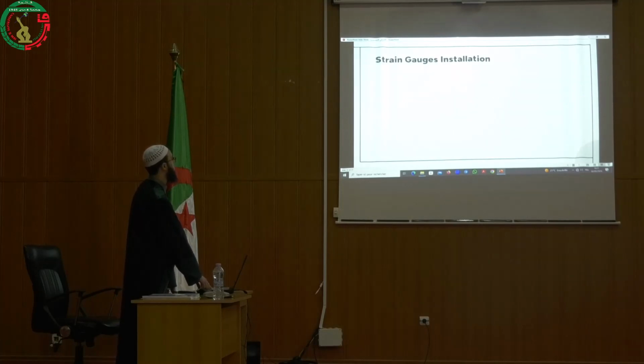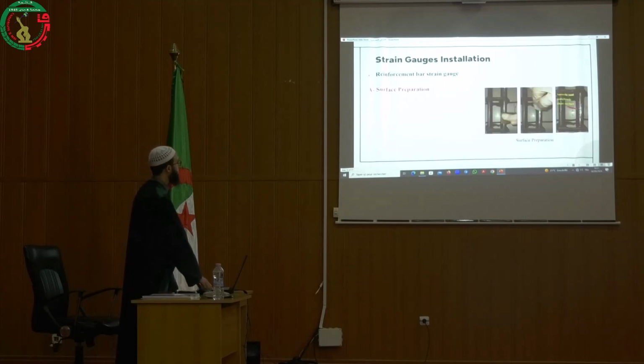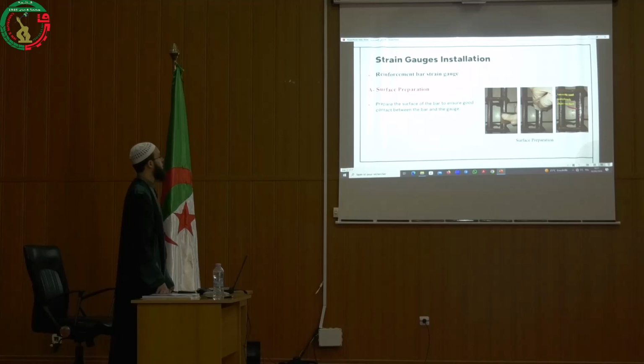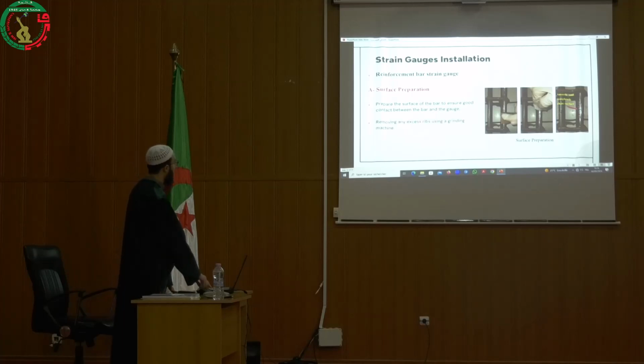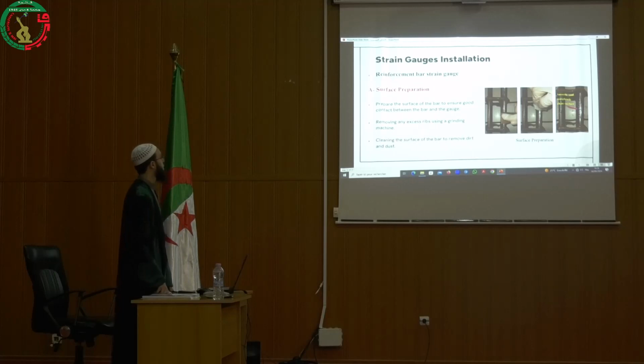The strain gauge installations. Strain gauge on the reinforcement bar. To install the strain gauge on the reinforcement bar, we first need to prepare the surface of the bar to ensure good contact between the bar and the gauge. This is done by removing any excess ribs using a grinding machine. Then we clean the surface of the bar to remove dirt and dust.